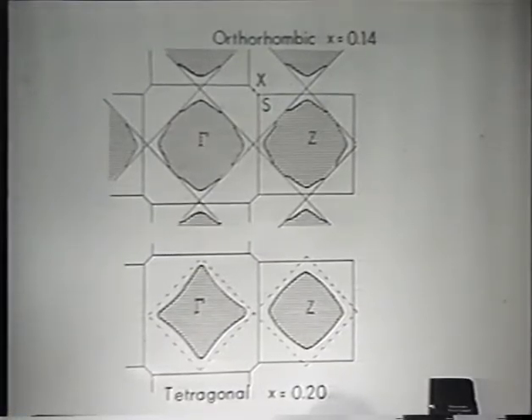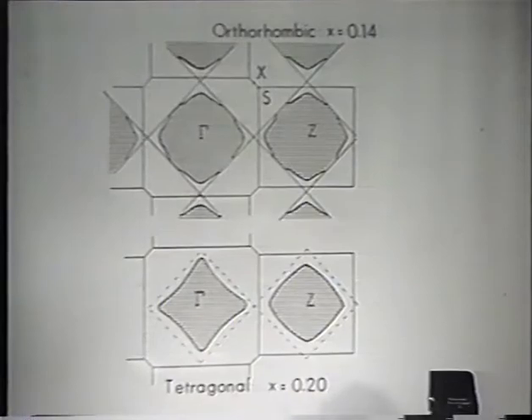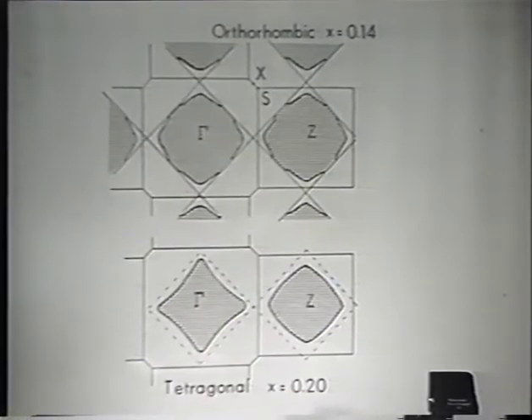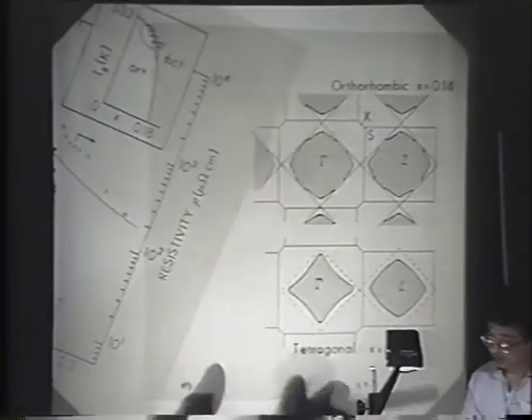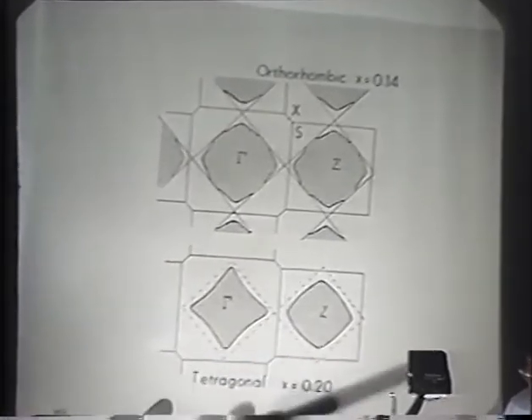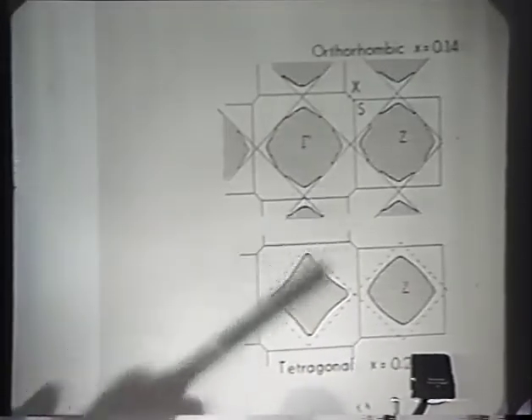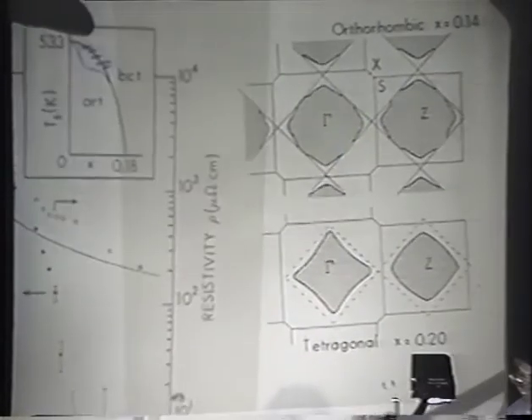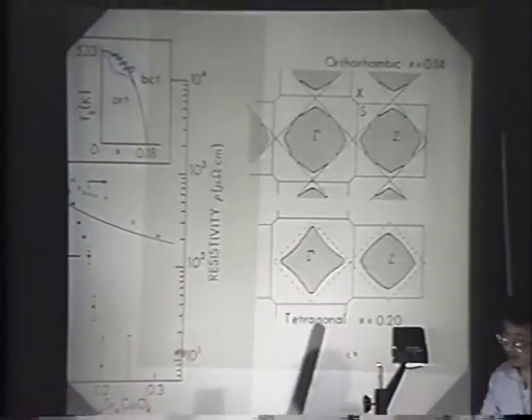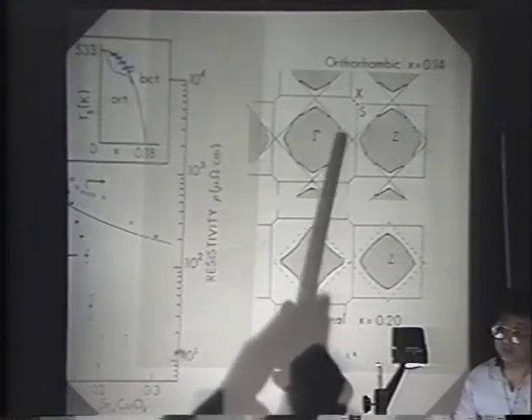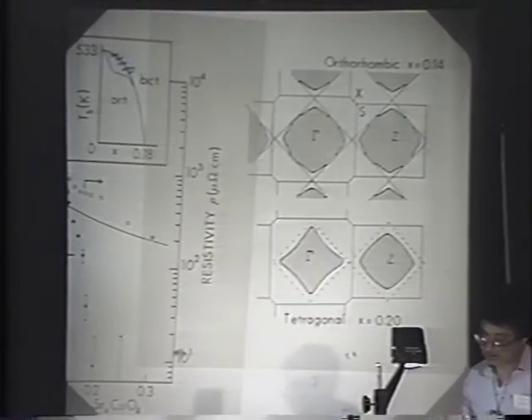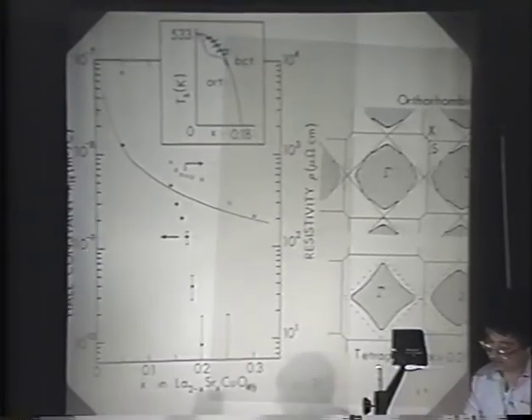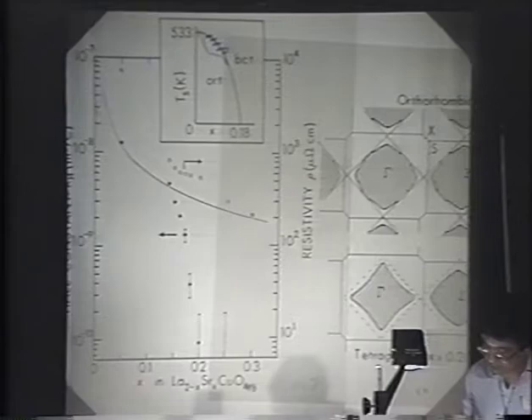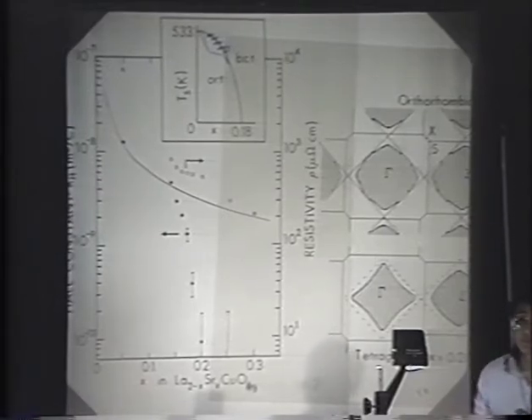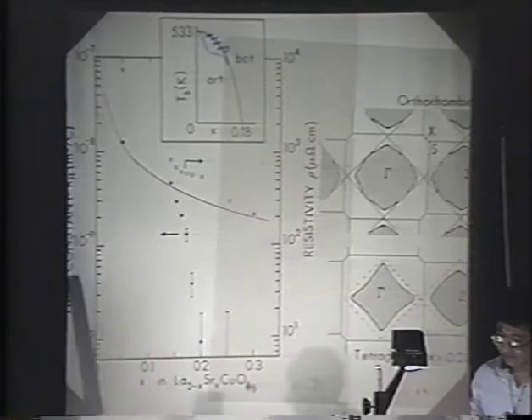I cannot have the situation where the gap follows the new Fermi surface. Otherwise, I would deviate from this line very strongly. The gap has to stay there, and then when I cross the tetragonal line, the gap disappears, and there's a rearrangement of the Fermi surface, and instead of very small hole pockets, you get very large electron-like pockets. So to sum up, my feeling is that the Hall signal rules out any destruction of a Fermi surface-driven instability between here and here. Thank you.